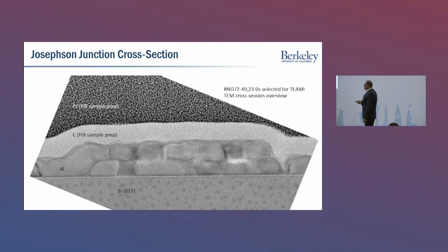So here's a high-resolution TEM of that cross-section of a Josephson junction. It's quite an exquisite picture taken by the LBL folks at the National Center for Electron Microscopy. You can see all the different grain edges of the little chunks in the aluminum piece. And you can see that little sandwich layer of aluminum oxide in between. It's not flat, it's not uniform, it's not pretty, but it's worked for 50 years. And part of that is because these junctions are very spongy. You can take out the strain by having this amorphous layer. So on average, they give you a very uniform tunnel current. If you start to look at fluctuations, that story may be very different.